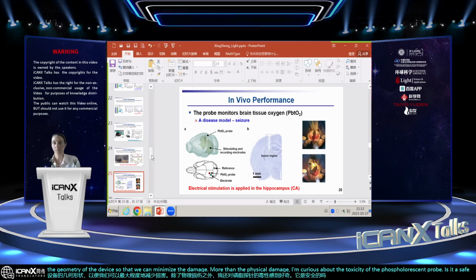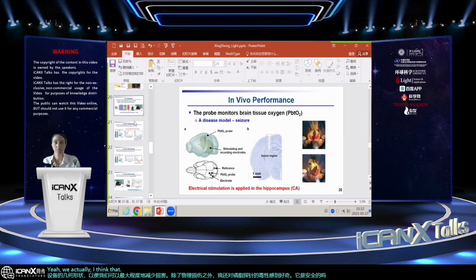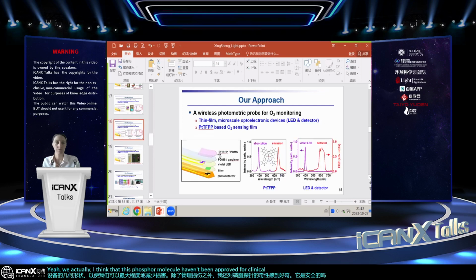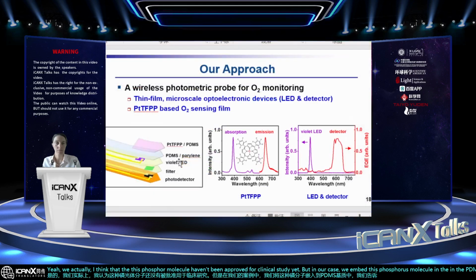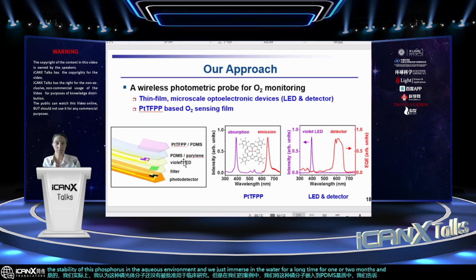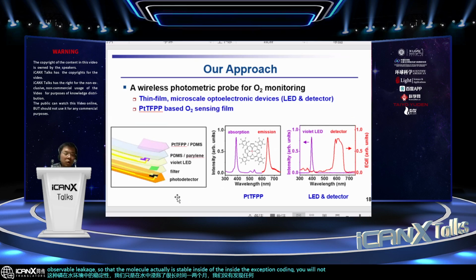Yeah, I think this phosphor molecule hasn't been approved for clinical study yet. But in our case, we embed the phosphor molecule in the PDMS matrix, and we tested the stability of this phosphor in an aqueous environment. We immersed it in water for a long time, for 1 to 2 months, and we didn't find any observable leakage. So the molecule is stable inside the encapsulating coating. It will not cause any leakage. And of course, for clinical applications in the future, we will have to do more serious investigations to understand this biosafety. Thank you.